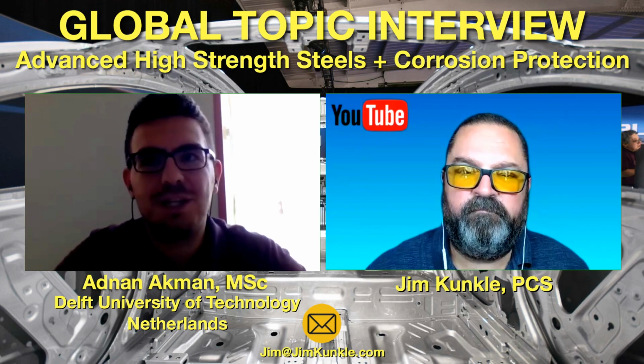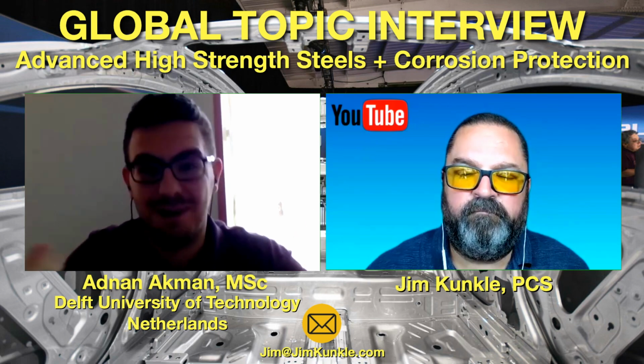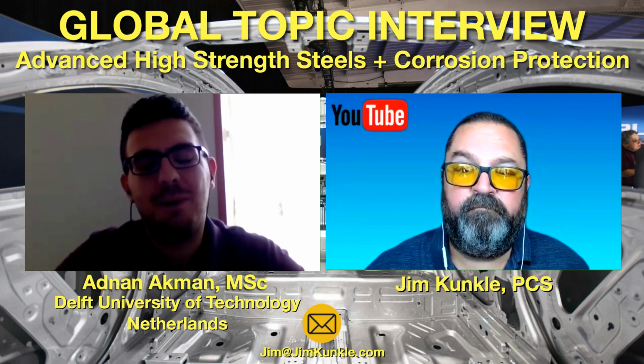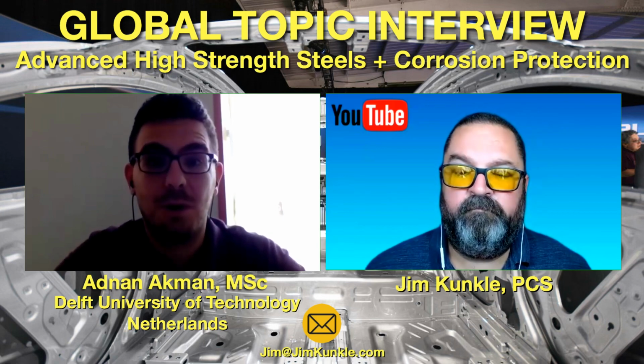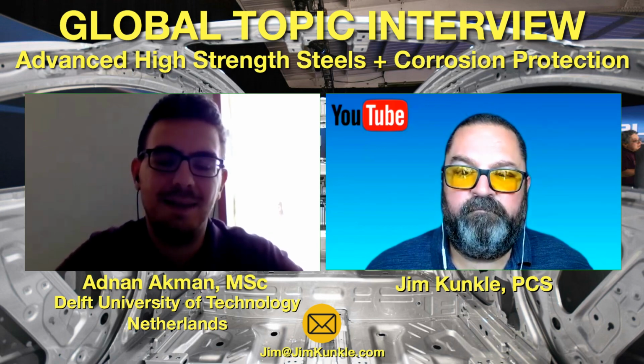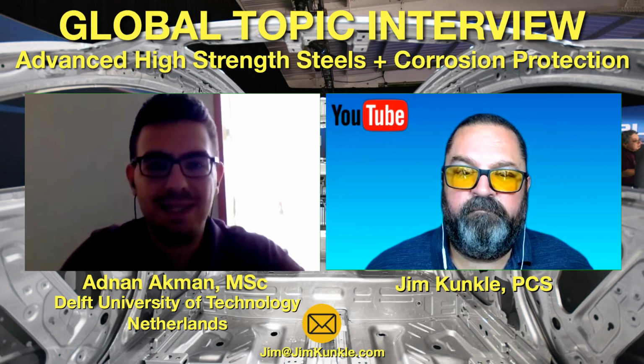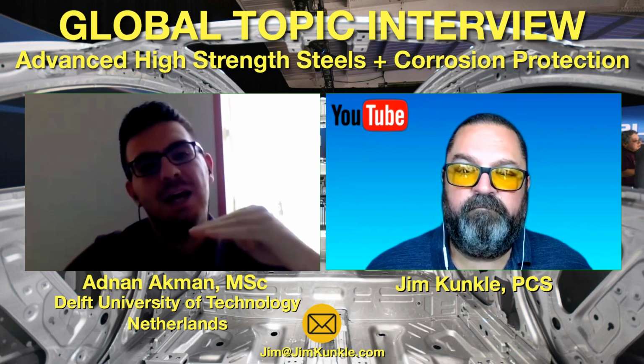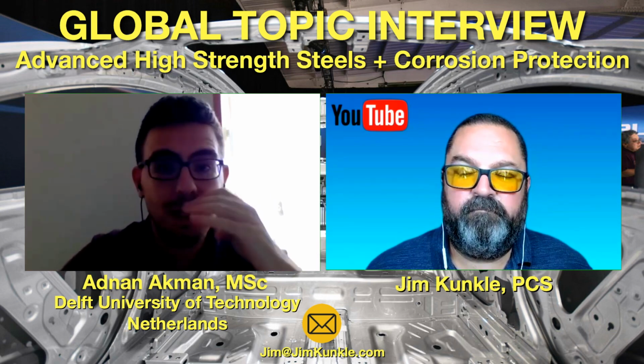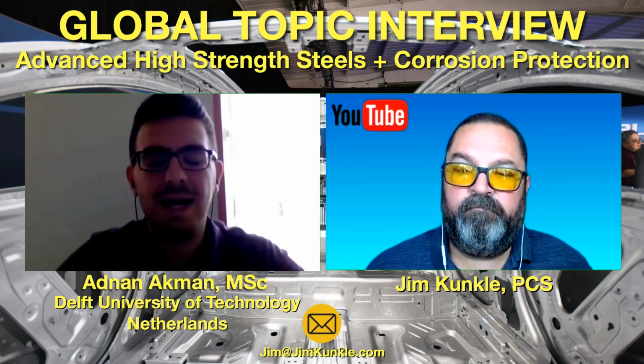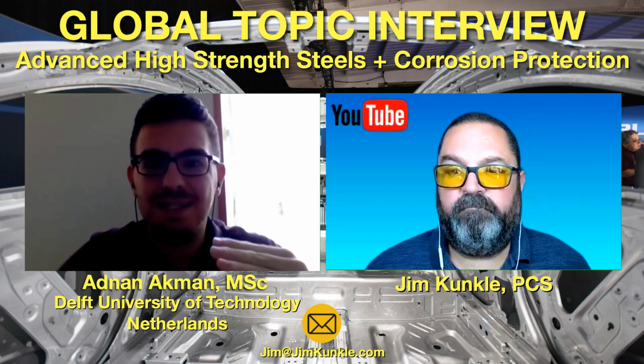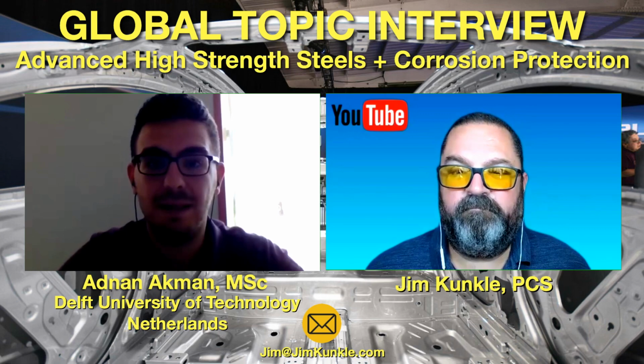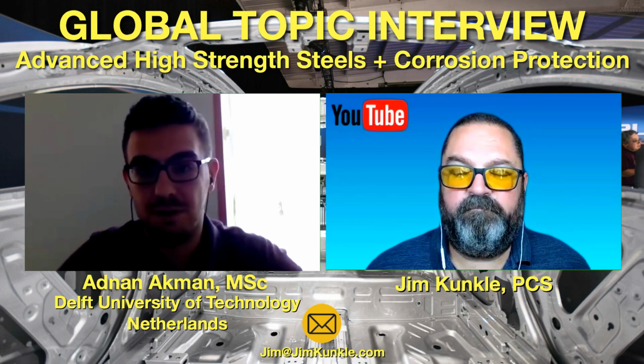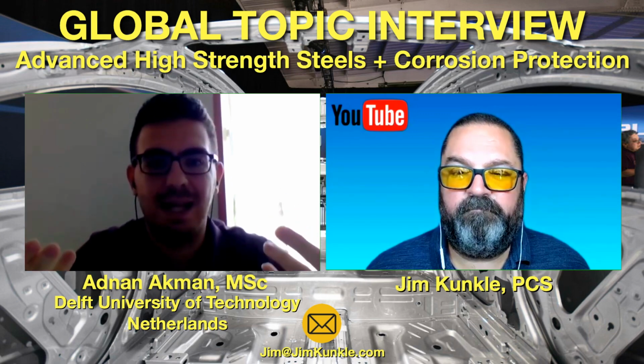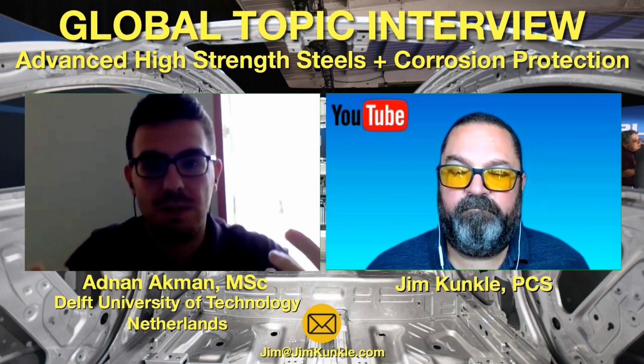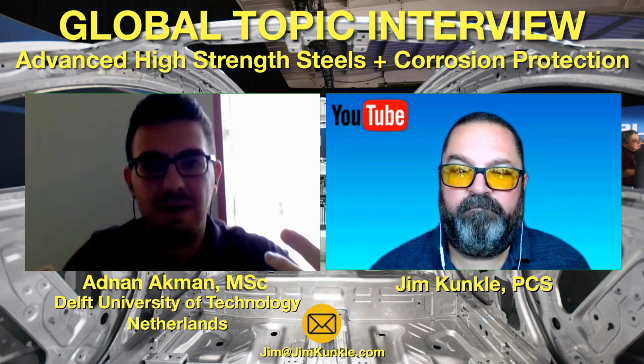But the cathodic protection techniques will not work well for automotive. So the most suitable way for corrosion protection is metallic coatings. Galvanizing is a kind of metallic coating. Basically, it is the formation of a zinc layer on top of the steel. Why? Because zinc will sacrifice itself to protect the steel. Zinc is anodic compared with steel, so in a harsh, corrosive environment it will sacrifice itself and protect the steel.